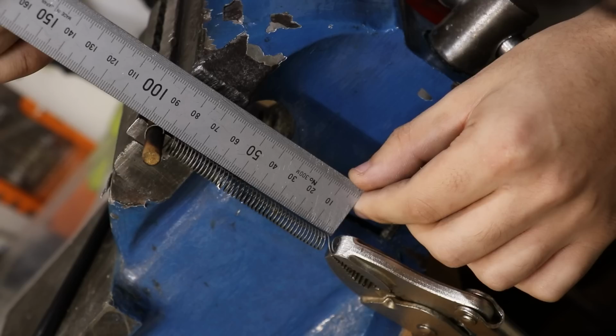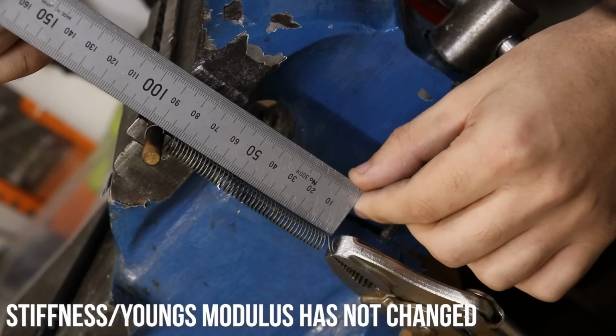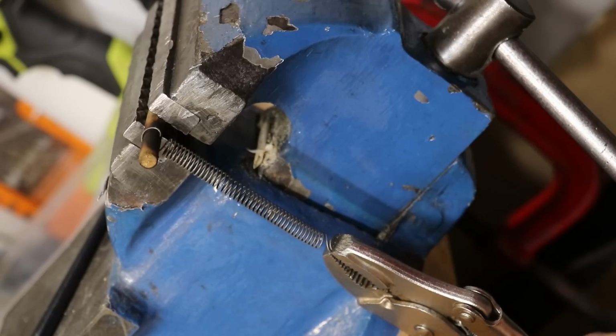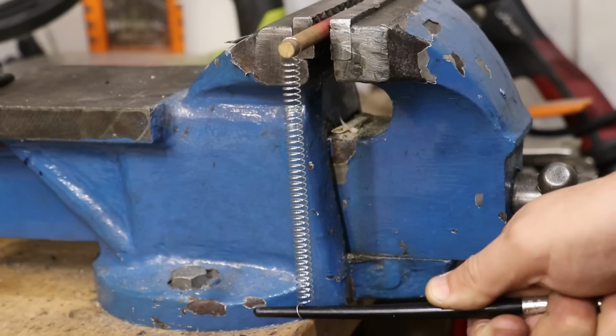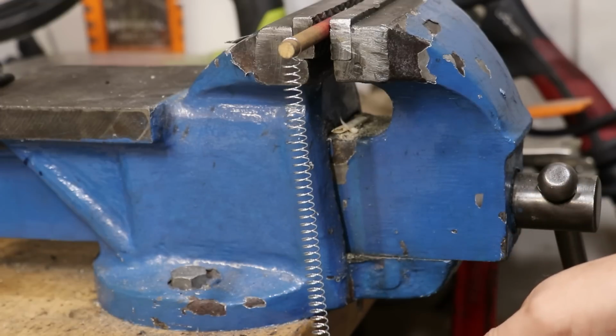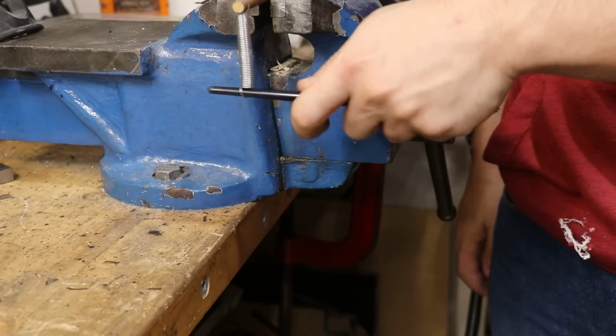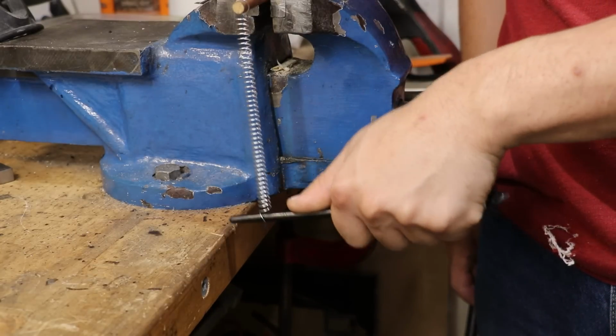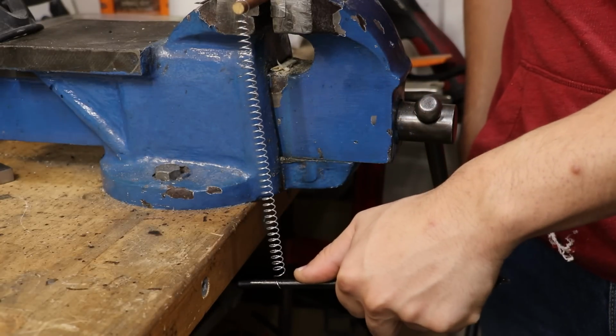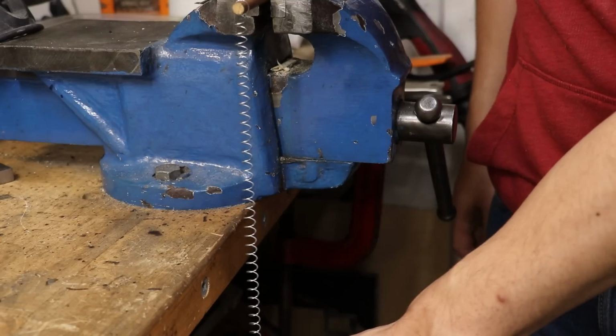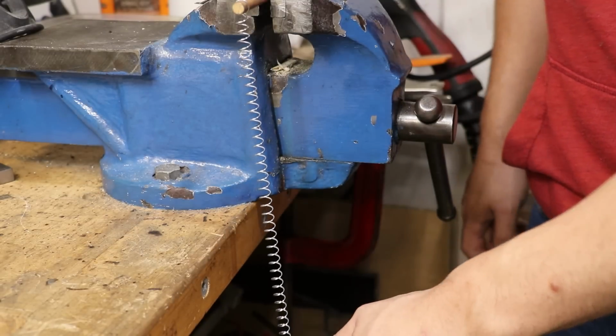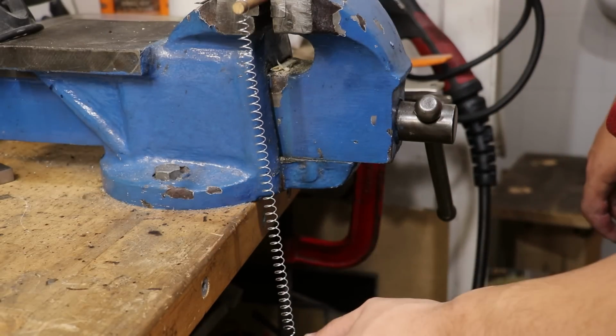A soft, unhardened steel spring is no more or less stiff than a proper hardened spring. And that's because the material stiffness doesn't change. What has changed though is how much force it takes to permanently deform it. Of course, it doesn't take that much force to permanently flex it, compared to beforehand, where it takes a lot more force to permanently bend it. And that is why springs are hardened, so they can take high loads without permanently bending. It's not to make them any more or less springy. And the same is true for metal rods, beams, or sheets.